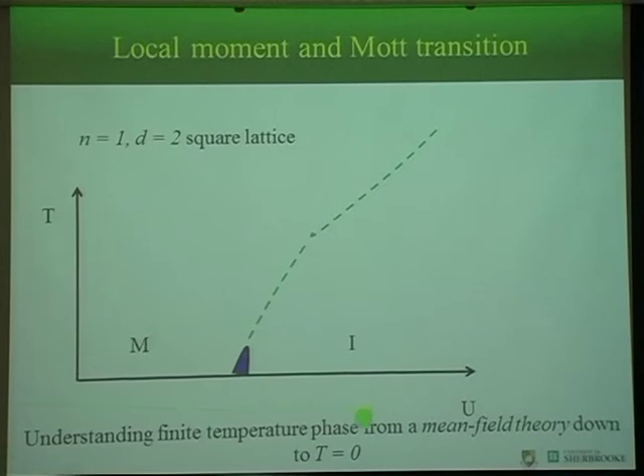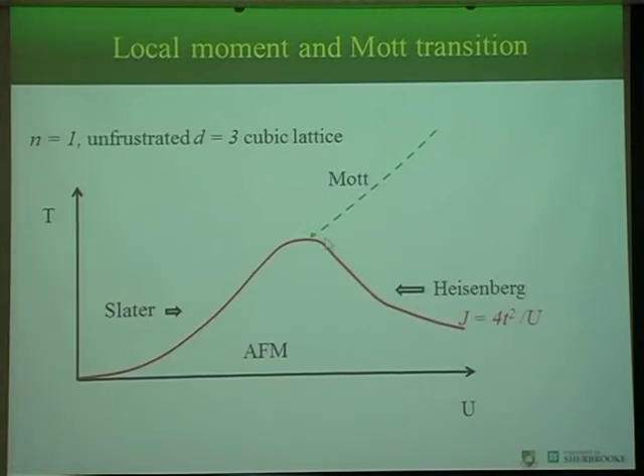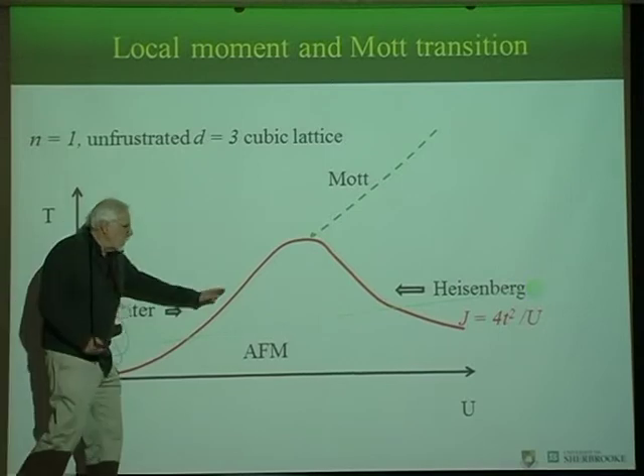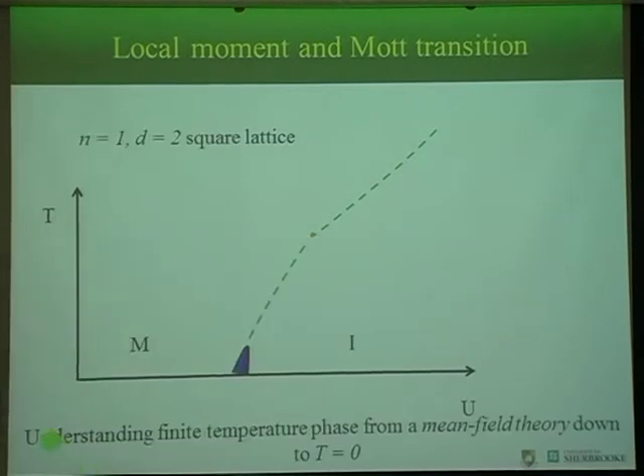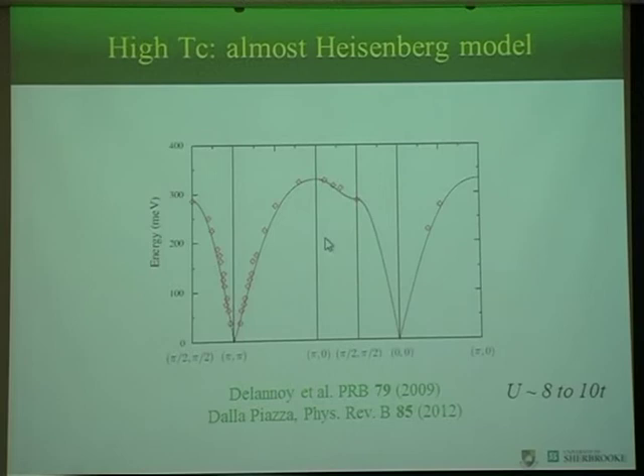Now, what dynamical mean field theory has shown us is that theoretically, you can remove this transition if you want, and then look at what would happen to this line. If you extend it all the way to 0 temperature, you get a dynamical mean field description of this line that Antoine will tell us about. That goes from metal to insulator.